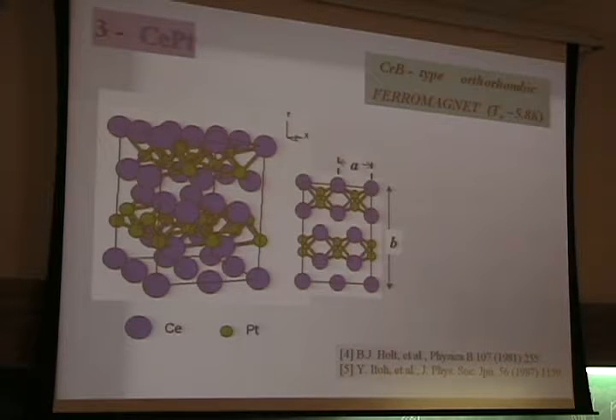okay, so let me present the system. The first system we work with is cerium platinum. It is a chromium boron type orthorhombic material. It is a ferromagnetic system with a TC of 5.8 K more or less.